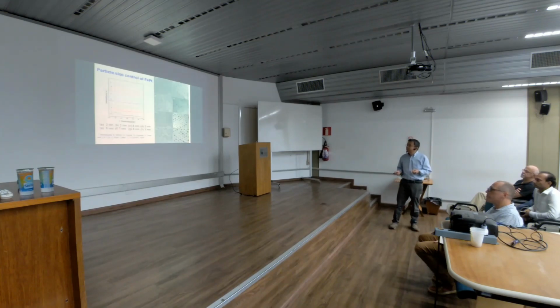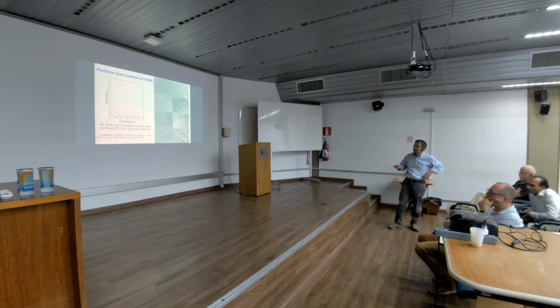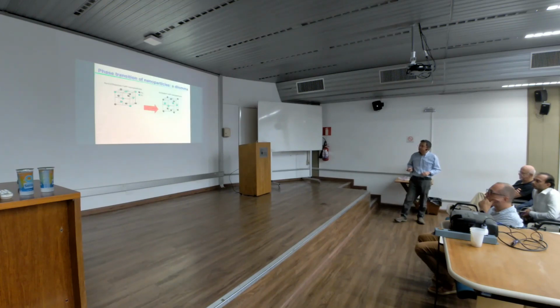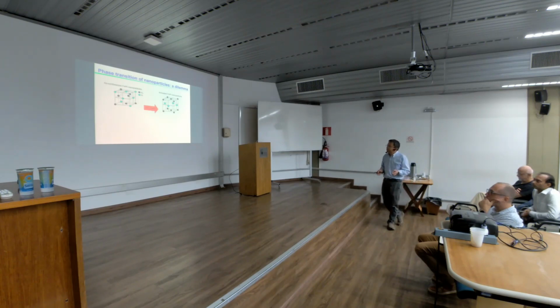So we start with the composition iron platinum. That is a good hard magnetic material. We start with particle size 2 nanometers and increase 1 nanometer by 1 nanometer. We could control the size with an accuracy of 1 nanometer. This is a TEM microscope image. This is XRD. You can see the overall picture, so you see the particle size change. And for iron platinum materials, people are very interested in them.